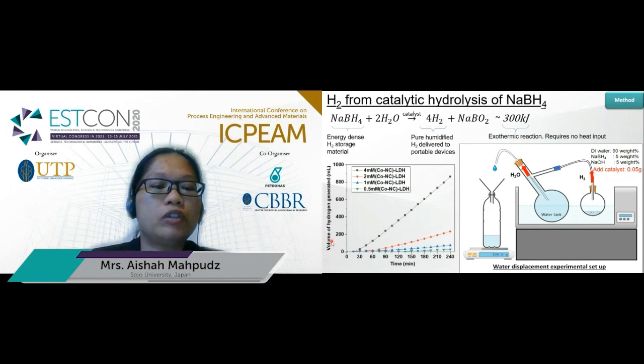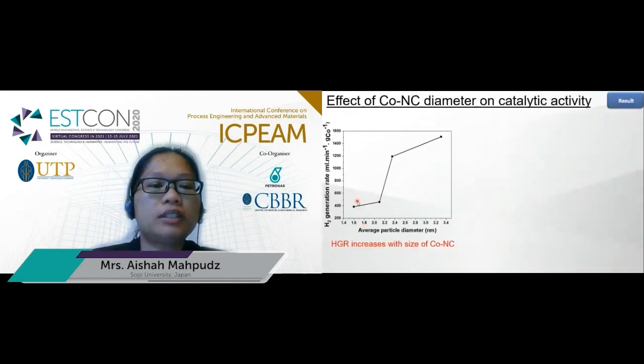From the graph, it shows the volume of hydrogen generated over time for all four samples. As you can see here, the hydrogen generated increases with the increase in the concentration of cobalt citrate solution. Essentially, this is the graph that shows the average hydrogen generation rate against the average particle diameter of cobalt nanocluster. So you can see here the hydrogen generation rate increases with the increase in particle size.